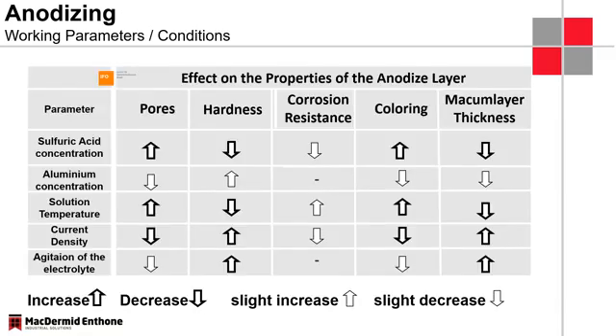So this is a chart everyone can use and then have a look at these effects and factors that drive the pore sizes and the hardness, so on and so forth. And most of this we talked about. So by increasing the sulfuric acid concentration, we get bigger pores, but because of the wall structure and the thinner walls, the hardness will actually reduce. The coloring, because of the higher pore size, becomes better with certain dyes. We have a higher absorption of colors or dye particles in these pores.